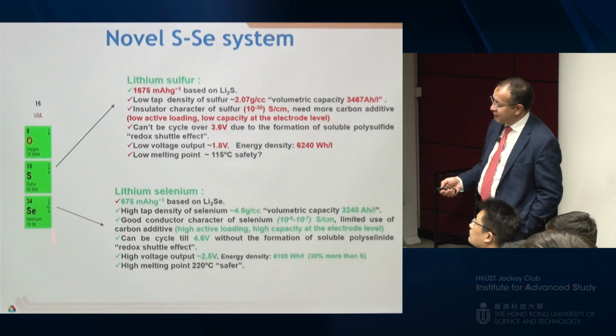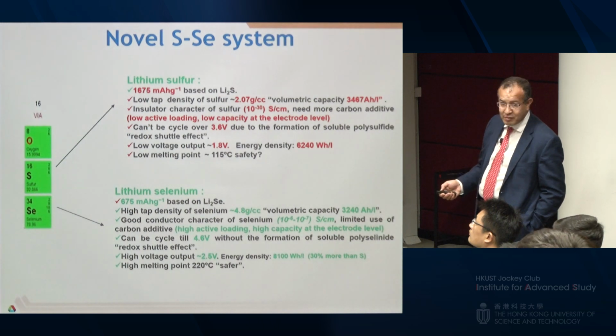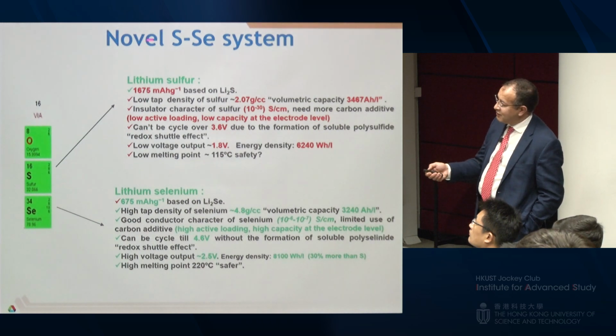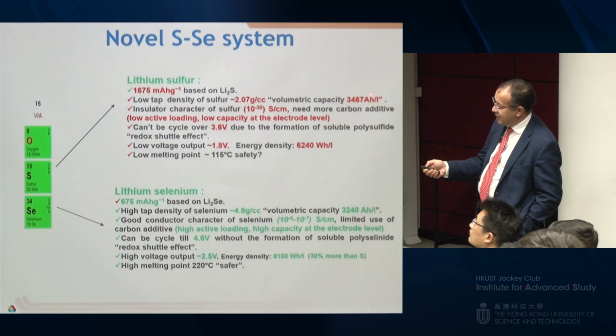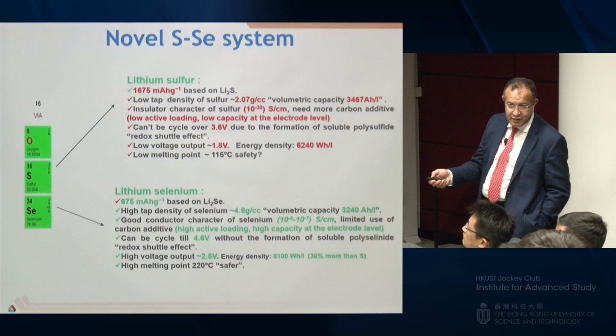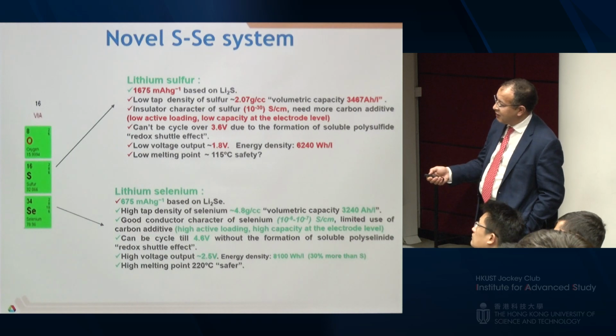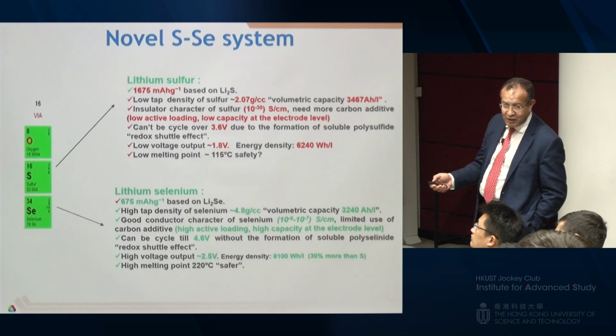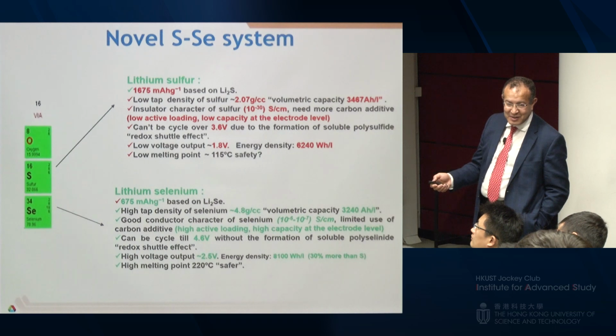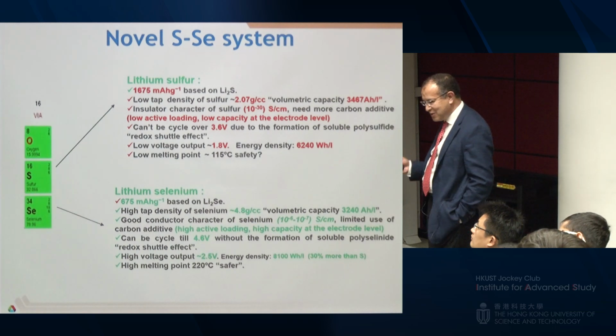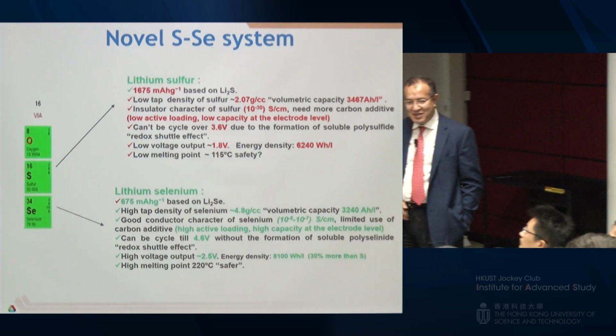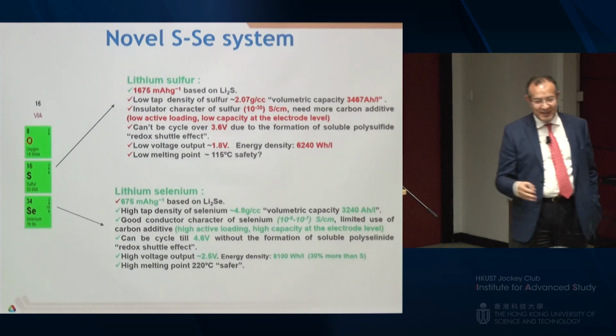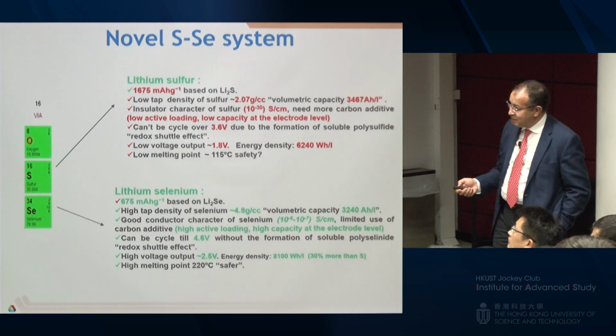If you look at the periodic table, sulfur is here and selenium is here. If you look at sulfur, you get high capacity, but the density is lower. Volumetric capacity is that much. Very insulating, which means you have to put a lot of active carbon to create conductivity. And it melts at very low temperature. You have to worry about that, because if your temperature of cells goes up beyond 115, you will melt your sulfur and basically short the whole system. Now look at selenium.